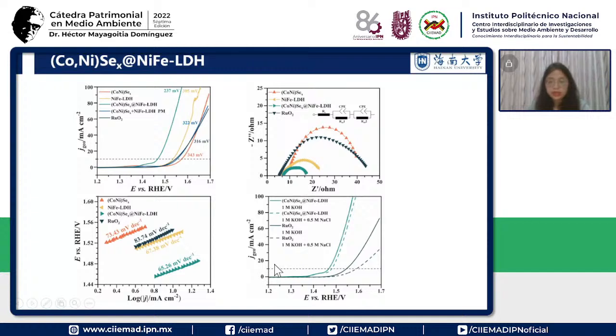And then we wanted to see what happens if we add salt, because we want to simulate seawater. So we add sodium chloride, and here we find, compared to only the alkali, the activity decreases just a little bit, but for the ruthenium oxide here, it decreases much.